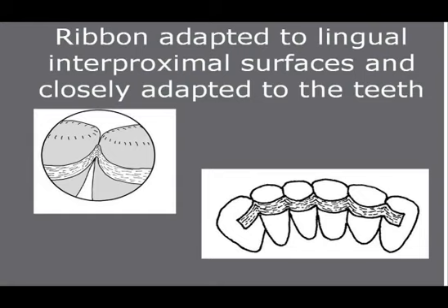We've not light cured anything. And this adaptation gives us a thin film of fiber up against the enamel surfaces. Once we've got the fiber totally embedded in the composite, covered with composite, as closely adapted to the enamel as possible, and placed in the interproximal embrasure spaces, interproximal contact spaces that are present, the lingual embrasures, we can then light cure. We want to make sure the composite does cover all the fiber and that we have minimal excess before light curing.